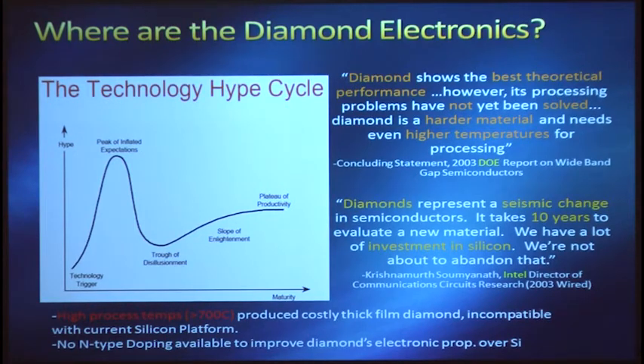So if we see that technology progresses in what's called a technology hype cycle, and we treat 1955 as the technology trigger and 2003 as the peak of inflated expectations, what's the trough of disillusionment? What do we need to move this forward? Well, we need 2 things. We need to be able to put diamond down cost effectively at lower temperatures so we can integrate it with silicon so that investment isn't lost. And we also need to be able to make diamond conduct similarly to silicon, at least better than silicon, right? So we want to say, same or cheaper cost and maybe 10 to 100 times the performance.